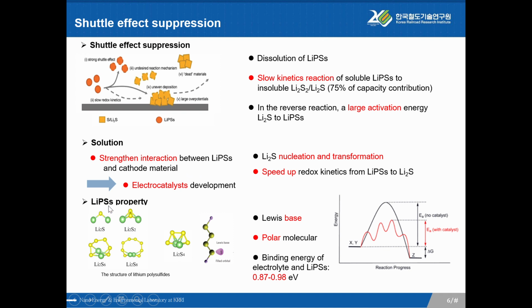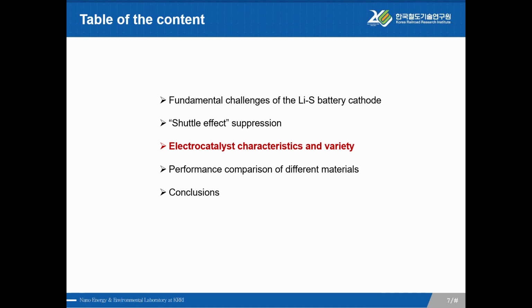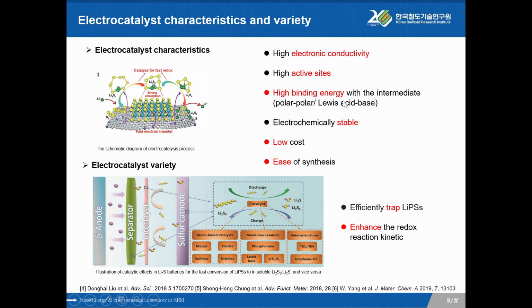So firstly, we should know the reactant property. The lithium polysulfide belongs to Lewis base and polar molecule, and the bond energy between electrolyte and lithium polysulfide is around 0.87 to 0.98. So catalyst should have a high bond energy with polysulfide, like polar to polar interaction or Lewis acid to base interaction, and should have high active sites, and also high conductivity, low price and easy synthesis.